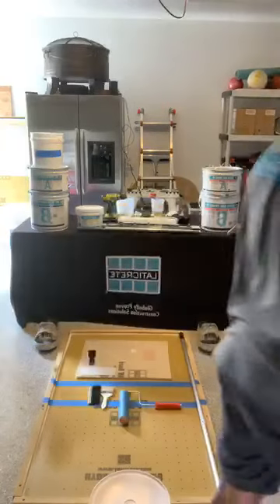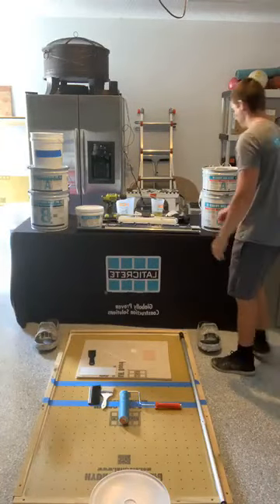And then we'll kind of just piece it together almost like a rapid fire so you can see the application of the products. So the difference between these coatings being a vapor barrier and not a general purpose epoxy: mil thickness is extremely important. In order for this to qualify and meet ASTM F3010, this one has to be at 12 mils, this one has to be at 16. Okay, so how do you do that? How do you measure 16 mils?